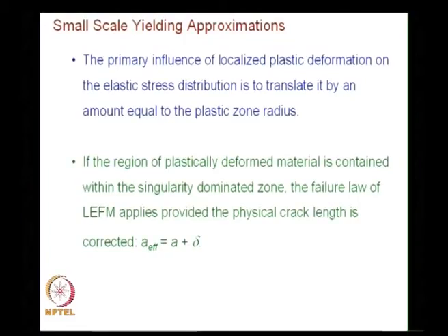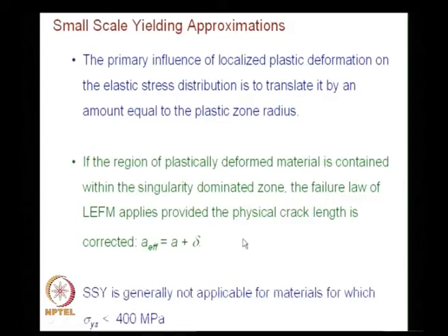We would see an improved calculation of this in the next chapter, and we have seen those expressions given by Irwin in this chapter. So, you have to replace it with these expressions when you do the calculation, but what it essentially says is LEFM is still applicable provided I change the crack length to A effective as A plus delta. And there is also another thumb rule that you have.